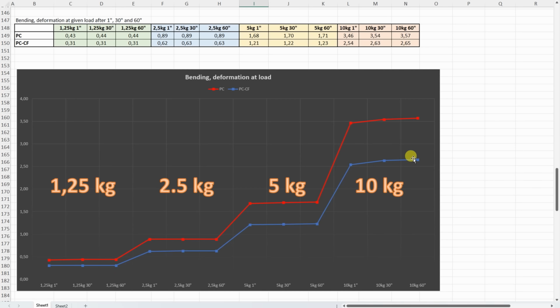Again, the PCCF was stiffer, and up to 5 kg this is not a big load for these materials. On 10 kg I could record some changes during the time, so this is on the edge of the maximal possibility of these materials. Torque or twist test with horizontally and vertically printed test objects, and I am starting with the horizontal ones.